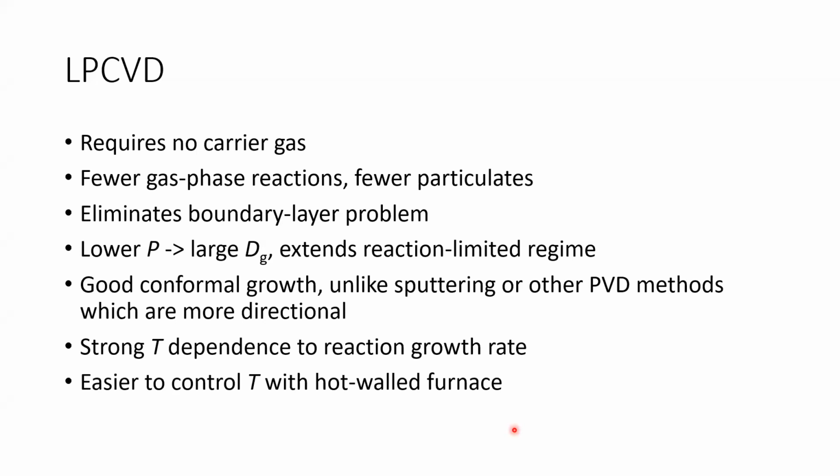It also eliminates the boundary layer problem because we minimize the boundary layer because of low pressure. And then we can extend the reaction limit region.